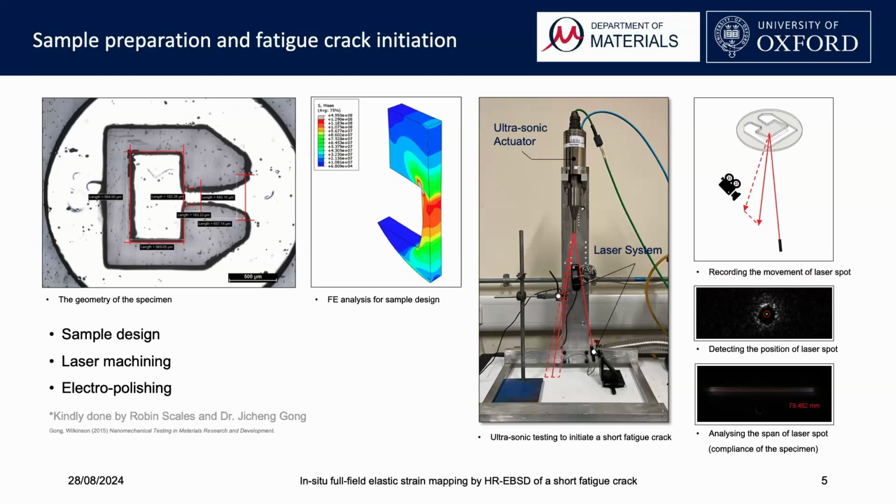The sample preparation and fatigue crack initiation was done by Robin Scales and Dr. Jicheng Gong, and I'll give a brief introduction. The shape of the sample was designed for perfect inertia during actuation, and each specimen was attached to this ultrasonic actuator. It can provide vibrations at 20 kilohertz. As the specimen moves, the hammerhead lags behind, which causes the neck region to bend repeatedly during vibration at